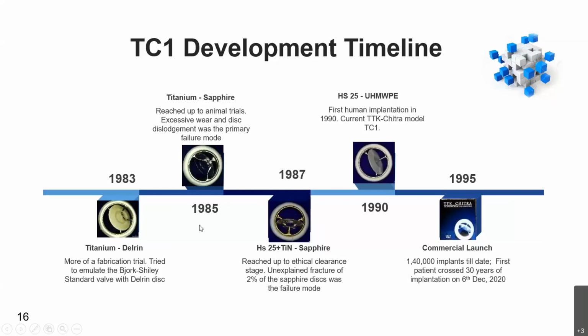So what we found in the case of this first model is that this particular device will fail after about 200 to 300 million cycles, and that corresponds to about 4 to 5 years or maximum 6 years life inside the patient, and this was not acceptable to us. So we started looking for alternate materials, and within 2 years we had a new model in which the titanium in the first model was replaced by a cobalt-based alloy, Haynes 25, and it had a coating of titanium nitride. This titanium nitride is a ceramic and is supposed to have extremely good blood compatibility and biocompatibility. And these are the two mandatory criteria for all materials which are used in medical implants.